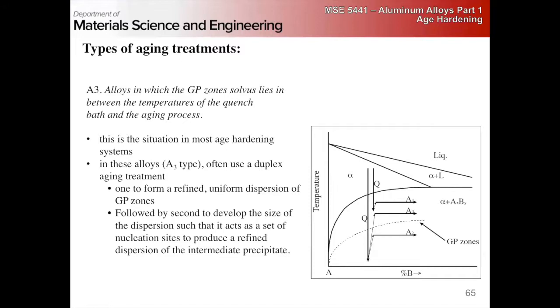Which is what we want in aluminum copper. Again, in the 2024, the magical aerospace alloy from World War II, right? It's used in a condition with a very fine dispersion of, not gamma, theta double prime, right? So quench, nucleate GP zones, raise the temperature. Theta double prime nucleates heterogeneously on the GP zones, which are then consumed and dissolved away.